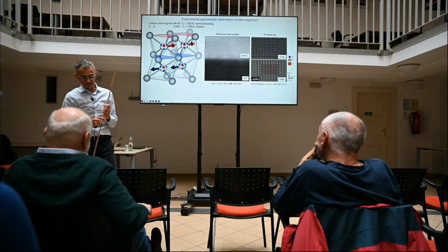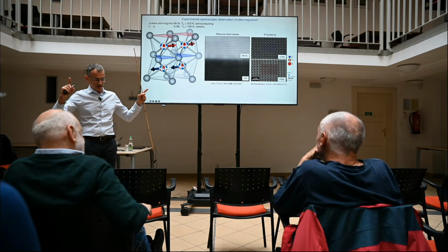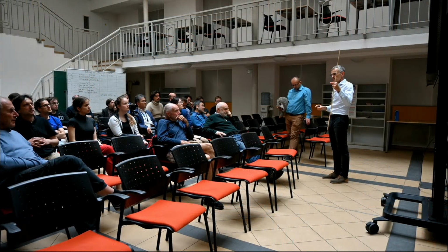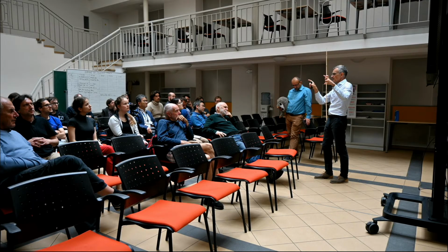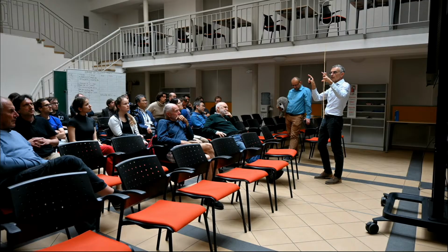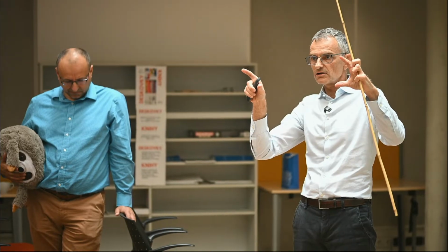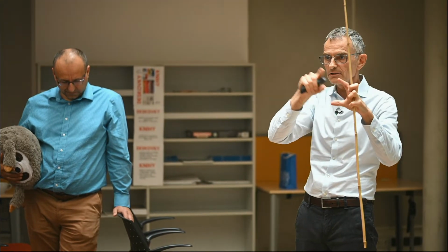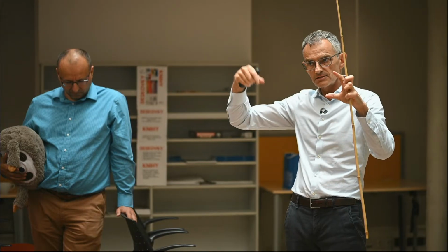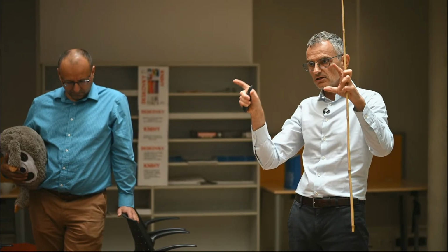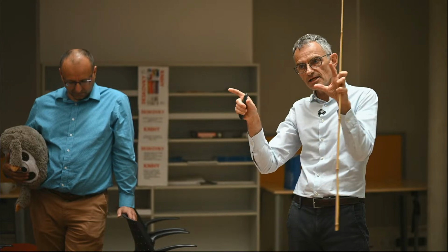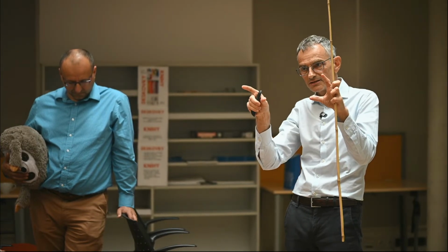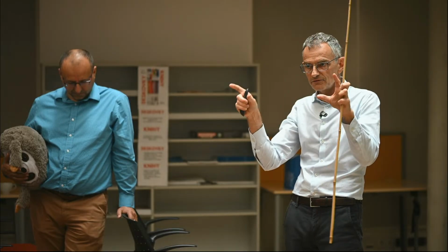So what you need for such a transition is a crystal where, for example, you have one spin and the opposite spin, and the crystal lattice environment, the other non-magnetic atoms in the lattice, are somehow mutually rotated. Okay? So that there is a rotation transformation from one to the other, which connects the opposite spin sites. If you have that, it's an altermagnet, and you simultaneously do not have the translation because the environments are mutually rotated. So you don't have the translation, and you also don't have the inversion.